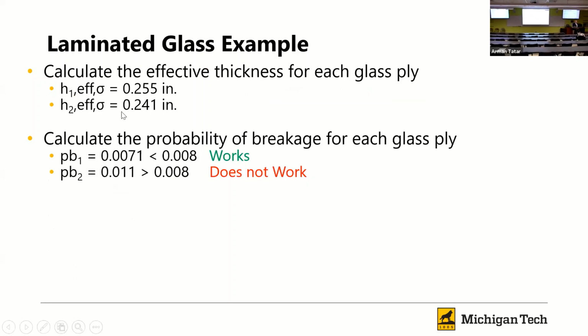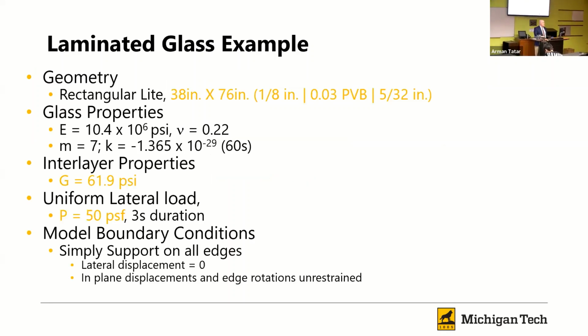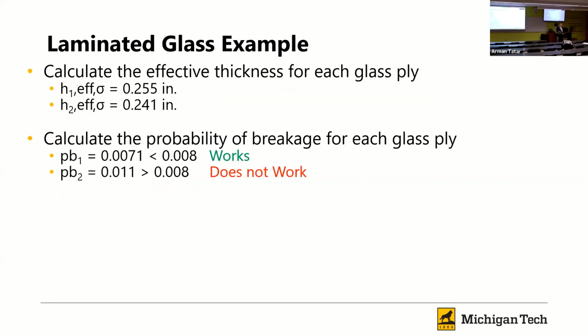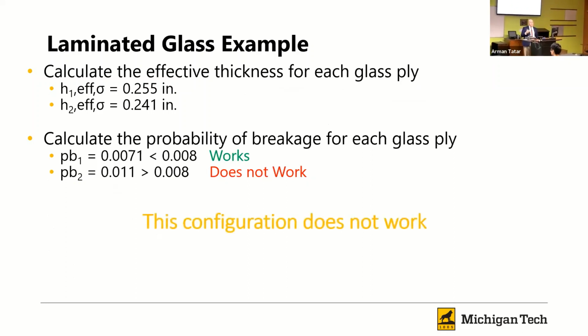And we perform those effective thickness models, and we've calculated probability of breakage, and we see that one of the lights worked and one of them didn't. Interestingly, in this case, the thinner one did not work. Is that right? Yeah. But depending on how it works and what heat treatment you have, that can flip around. So since that doesn't work, this design doesn't meet our requirements.